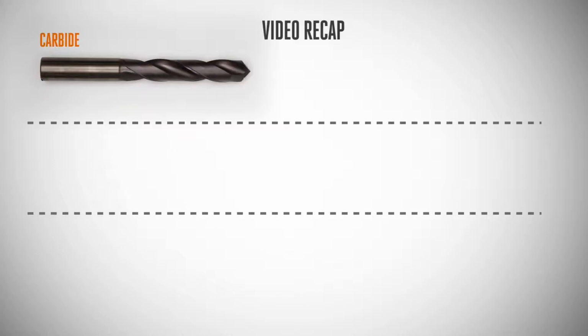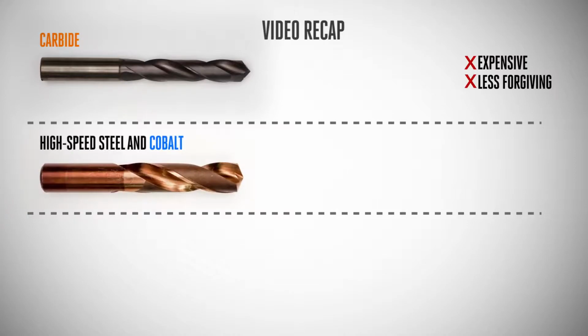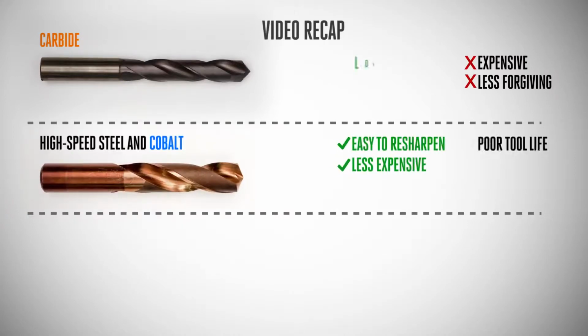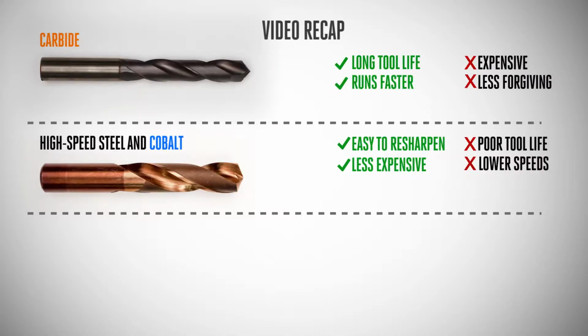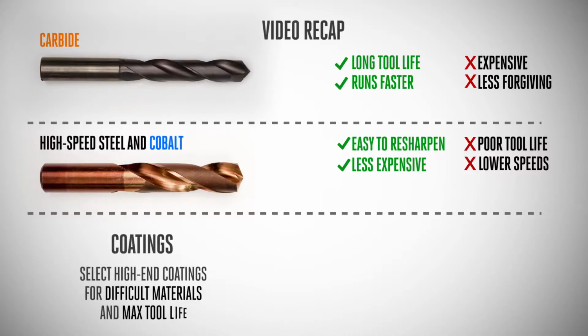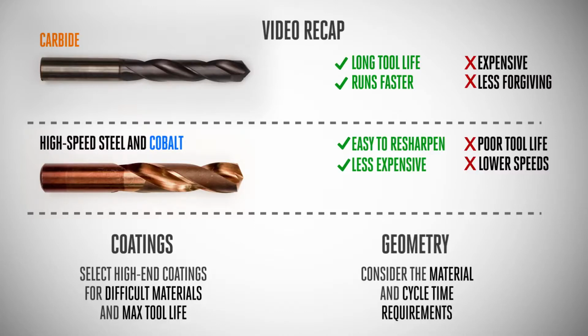So let's do a lightning fast recap. Carbide is much more expensive than the others. It's also less forgiving if used incorrectly. High-speed steel and cobalt are easy to resharpen, but don't offer anywhere near the tool life of carbide. Typically, carbide can also run significantly faster. When it comes to coatings, if you're machining difficult materials or need max tool life for long part runs, then select the high-end coatings. And for geometry, we're just touching on some of the aspects, but consider the material and your cycle time requirements when deciding which way to go with each of these elements.